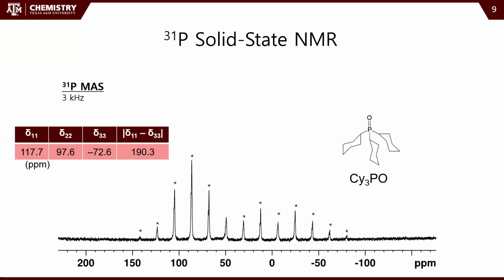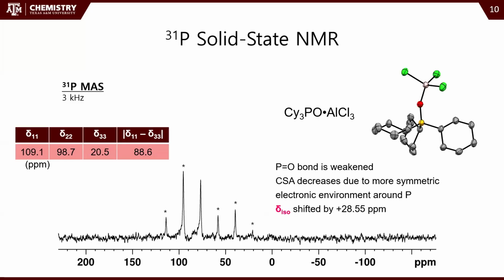δ33 values there. And then as we make our adduct, the adduct is having a much reduced chemical shift anisotropy. And that's because the strong Lewis acid's pulling that oxygen back, right? And so the phosphorus is feeling less influence from the oxygen, and so that dipole is being reduced. And so because we have a smaller dipole, we have a smaller chemical shift anisotropy. Also, we see the isotropic peak is shifted up by about 28 ppm, and so that's just indicating that the phosphorus is more deshielded overall, which is what we'd expect from these.